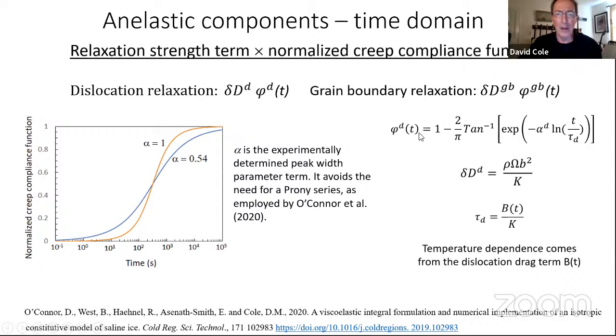Take a step back and think of what we're actually doing, how we're accounting for this analytically. Anelasticity is a time-dependent process. If you were to use a standard anelastic solid single relaxation time analysis, you would find a time dependence that would follow this orange curve here where I have alpha equals 1. In material science circles, that's a Debye relaxation process. It turns out that if you have one relaxation time invariant for your sample, this is the behavior you get.